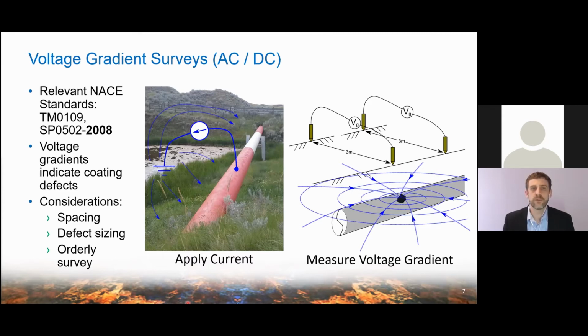Now, in terms of the voltage gradient test itself, this is basically the setup. You attach to your pipe and you apply a DC or AC voltage source, and then you discharge current from a temporary or permanent ground bed. And when you do that, you're going to have current which is discharged from the ground bed and picked up on the pipe. And this is basically what I'm trying to represent over here.